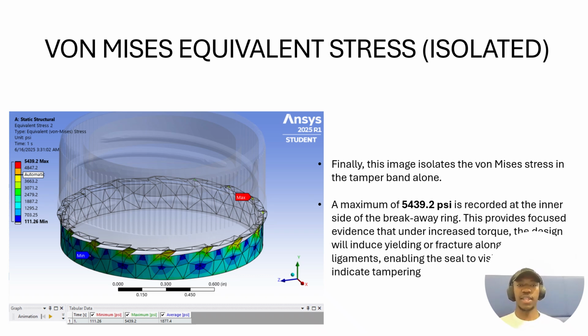This is a second slide that shows the equivalent von Mises stress. But this slide is different from the first one, because the first one showed the von Mises stress for the whole cap, and this one specifically shows the isolated von Mises stress on the lower portion of the cap, because that's really where the tamper seal is, in those notched ligaments. Here we can see that the maximum stress is localized at about 5,000 psi, which is recorded on the inner side of the breakaway ring, and this precisely helps us ensure that if the cap fails, it does so in the ring, not somewhere else we didn't expect.